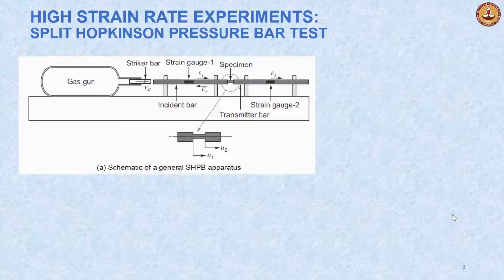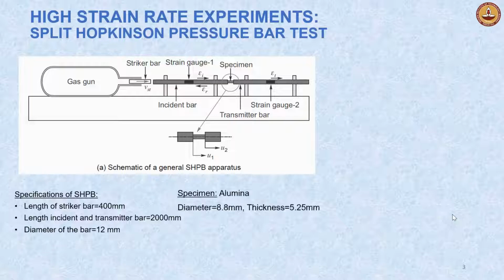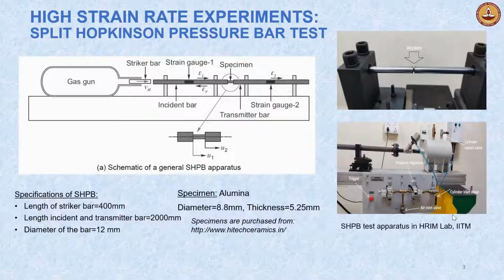Specifications of SHPB in the high rate impact measurements laboratory are given here. In this study, alumina ceramic is tested using SHPB. These are some images of the test setup in HRIM Lab. For the high strain rate testing of brittle material like alumina, pulse shaping technique is required to achieve constant strain rate and dynamic equilibrium conditions.